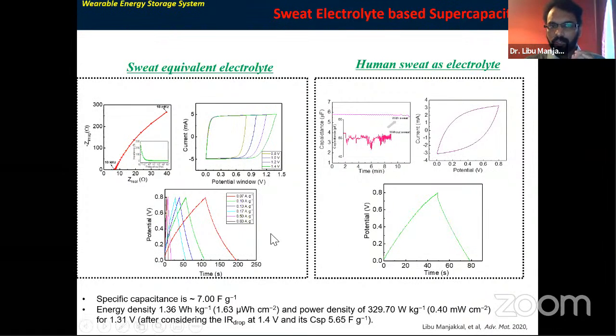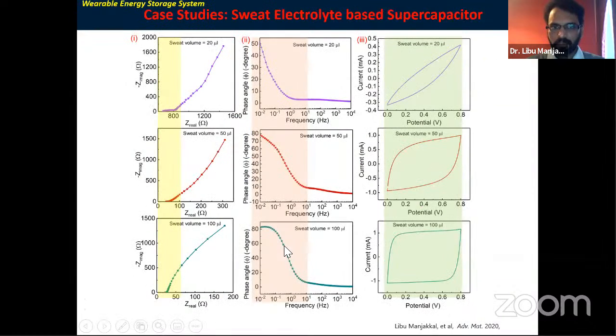Then initially I started with a sweat-equivalent solution in my laboratory, and then I measured the performance. Then with human sweat as an electrolyte, I compared the performance using CV, EIS, and GCD. I observed that in the dry condition, when there is no sweating, it's like an open circuit condition, and the capacitance of that device is in picofarads. It means that not many ions are stored on the surface. But during sweating, when ions take part in the electrochemical reaction, the capacitance increases due to the storing of the ions. And then I measured the specific capacitance, and I found that both devices, sweat equivalent and human sweat, show almost similar performance.